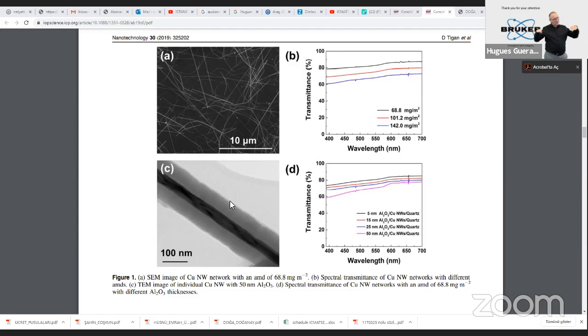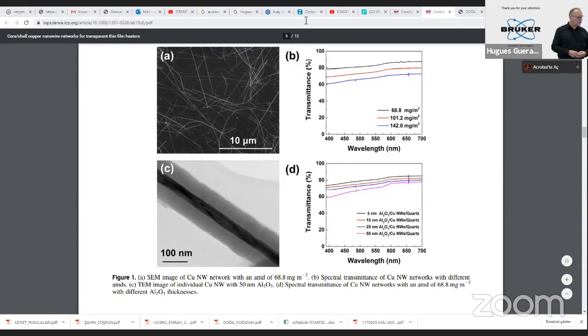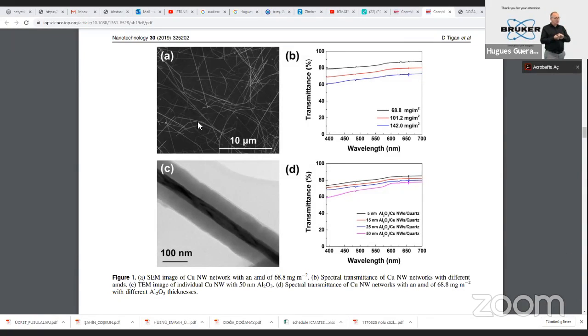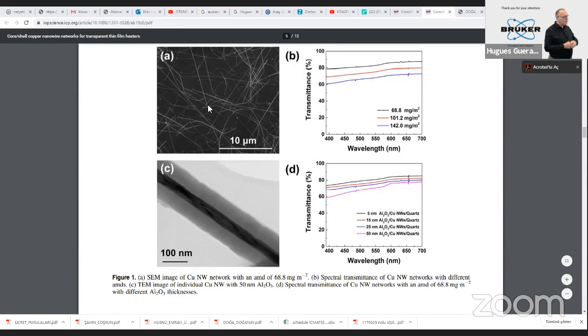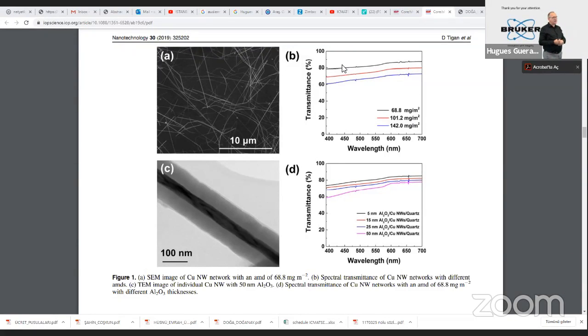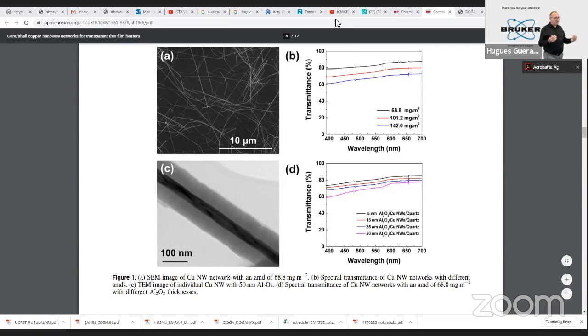So I would advise you go into grazing incidence and perform your detector scan, and you should observe the crystallinity of the different components here. The only risk is if you have a coating around that is too thick and really covers your wires too much. Maybe you have a problem of penetration through the surrounding coating, and then you cannot see the material inside. So this is all about X-ray absorption.